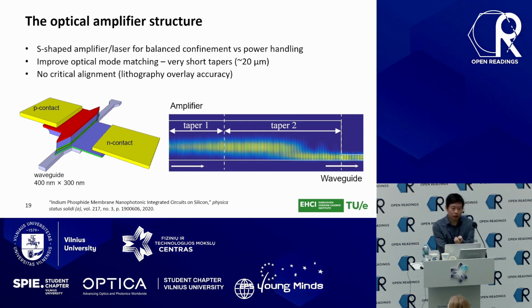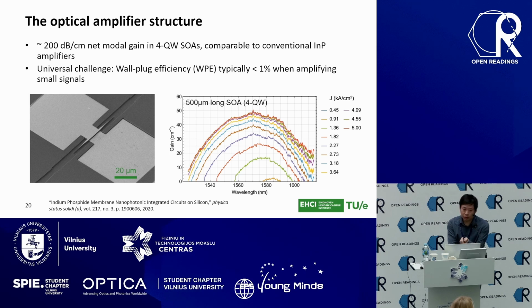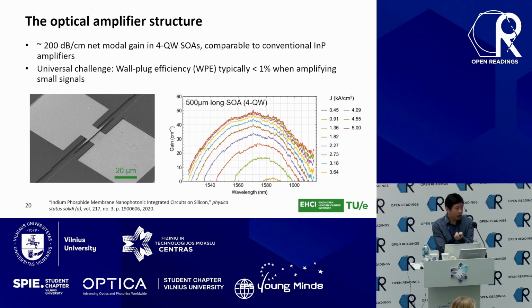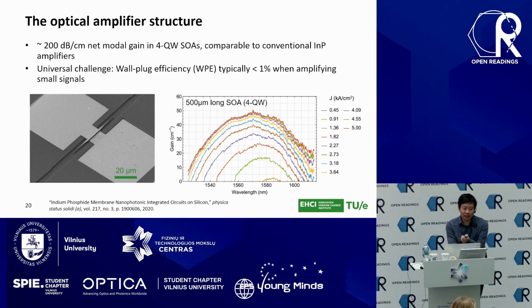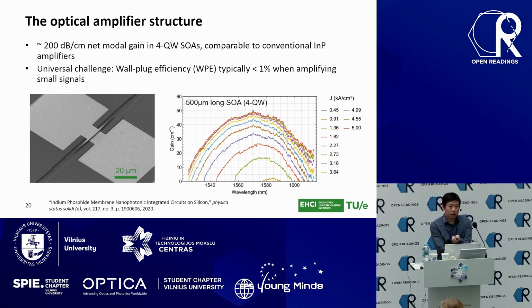So it leads to a very compact taper structure of only 20 micrometers or so. And because it's the same material system, we can process it in the same process flow. It means the taper structure can be aligned very accurately with the passive waveguide because it's done by lithography. So this is the example of the amplifier we created on this very thin optical membrane. About 200 dB per centimeter gain we can achieve in a 4-quantum-well system, which is very comparable with conventional indium phosphide devices.